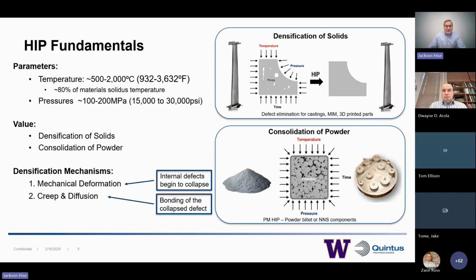Looking quickly at the fundamentals of HIP, if you're unfamiliar, hipping revolves around applying temperature and pressure. So our temperatures are going up to 2000 degrees Celsius, but this is really material dependent. Here we're looking at only about 80% of the material solidus temperature. We're also applying pressures up to 200 MPa, and the first and foremost use of HIP is to densify solids. We see that in traditional cast variants, hipping has been used on mission critical components for many decades.